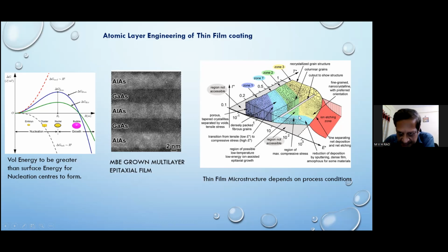It may be a single crystal, suppose we want. In that case, we need to use low deposition rates and appropriate high substrate temperatures, so that appropriate energy is imparted to the atoms to move around and hold. If the temperature is too high, that is also a problem, then it will again re-vaporize.